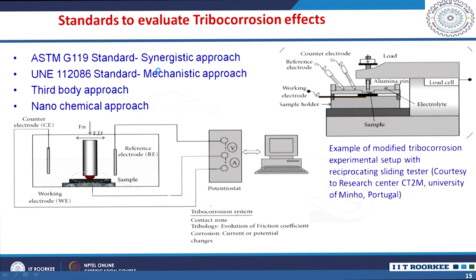Finally, there are several standards available to evaluate such tribochemical effects, or we can say tribocorrosion effects. There is one ASTM G119 standard for the synergetic approach of wear because of the mechanical contacts and wear because of the corrosion effects. Both can be synergetically estimated. The wear by synergetic approach can be estimated by this standard, or the UNE 112086 standard for the mechanistic approach, or the third body approach, nanochemical approach. There are several standards available to evaluate such tribochemical wear, right?